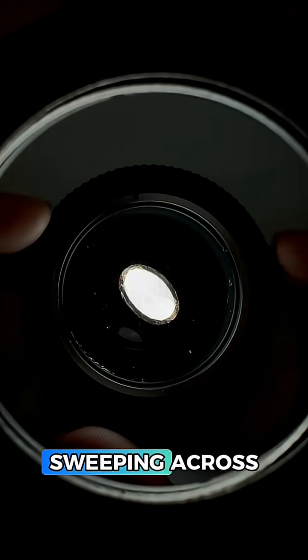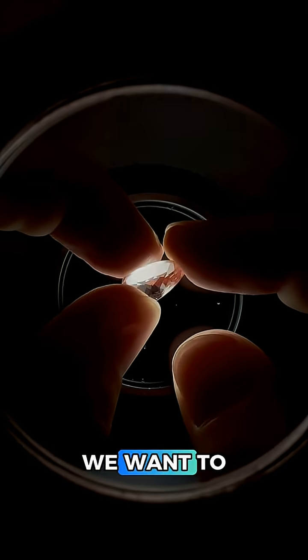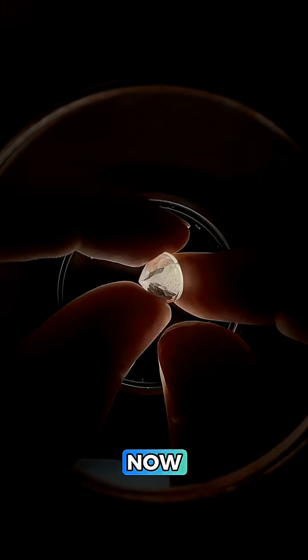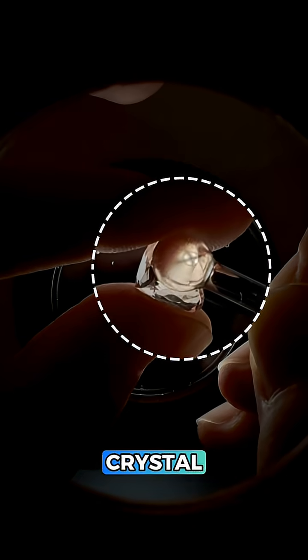We're getting a very clear brush sweeping across the gem and if we follow where it points, we can often find a crystal axis. Picking up the gem, we want to search for rainbow-like interference colors to find the crystal's axis, and here they are. Now we can use a condensing sphere to get an optic figure and we're getting a cross, which indicates this is a uniaxial crystal.